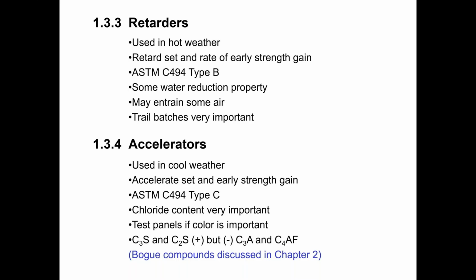Accelerators can also cause color variation within the concrete, light and dark areas. So generally, you're not going to use an accelerator in any mix where aesthetics are a high priority. So if you do need to use an accelerator in a precast unit where aesthetics are important, then you definitely need to do some trial batching just to see what the effect of that accelerator is going to be and whether that can be accommodated within the mix, within the project requirements. Again, the warning with regard to chlorides. Chlorides do make very good accelerators, but again, most admixture manufacturers can provide you with a very effective accelerator that does not incorporate additional chlorides. But it's a good question to ask.